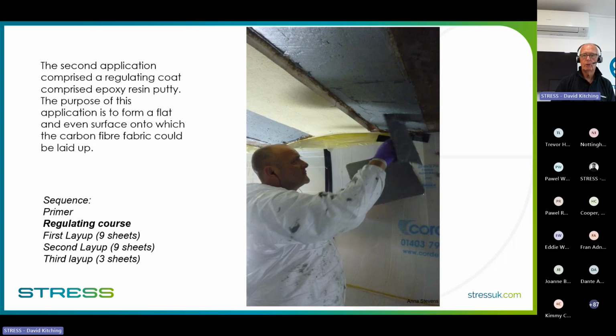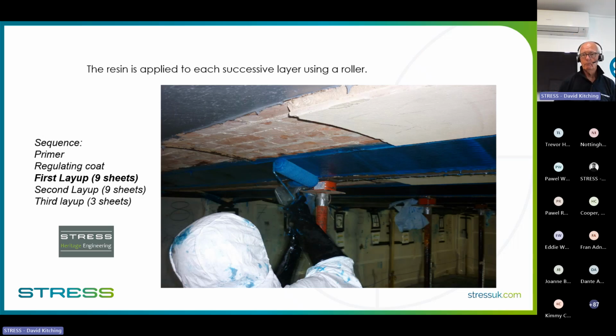So we've got one of our guys here, John. He's worked for us for over 25 years now. He's a master plasterer and screeder, and I think he's the only guy I've ever seen who can handle what is a thixotropic epoxy adhesive or putty, and actually make it go the shape he wants it. And so every one of those had to be in a curve and smooth, so that when you then bond the carbon fiber to it, you get a full 100% intimate bond. The putty, of course, goes into all the little shapes of the brickwork, and you get a full bond on that. So that's what we call a regulating coat. And then we can start to apply the carbon fiber sheet.